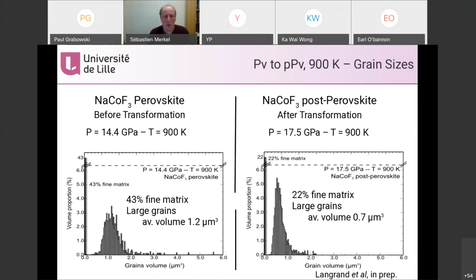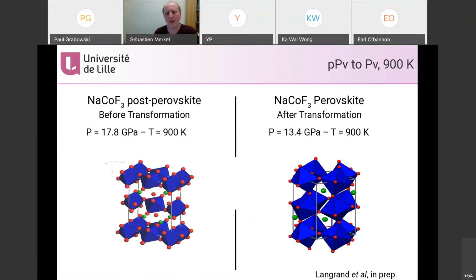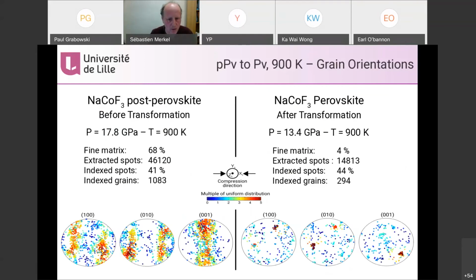You can also extract grain size distributions based on these measurements. I won't go into the detail, just so you know you can do it. Now, what I want to see is what happens if you go back, if you go from post-perovskite to perovskite. Is it the same mechanism or is it different? So now we're going to go from post-perovskite at 18 GPa, and we're going to lower the pressure to 13 GPa. And these are the results.